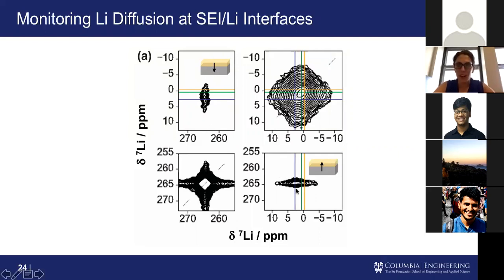But then we also have these things called cross peaks, where you see this cross peak here, and it comes in at a chemical shift that matches with lithium metal in the SEI. And then we also have this cross peak here that matches up with lithium metal and the SEI. So you can see the center of mass is sort of over this lithium oxide peak, which tells us that lithium ions are exchanging between lithium metal and the passivating lithium oxide layer that's just naturally on the surface of all lithium metal because it's so reactive.